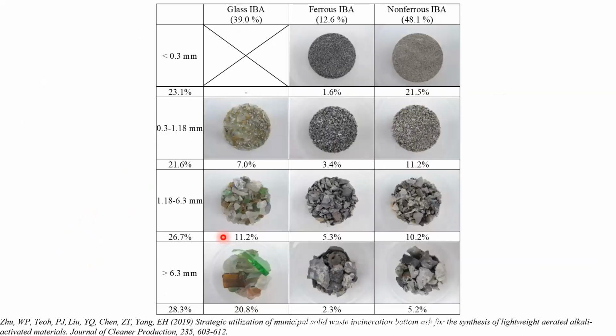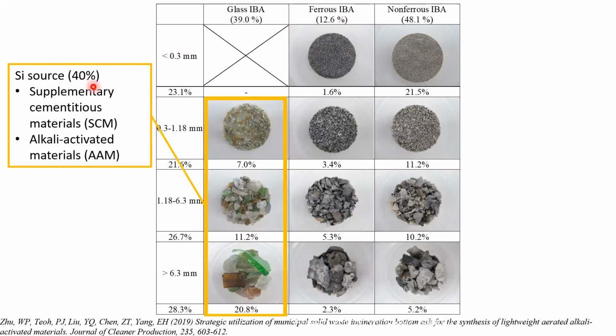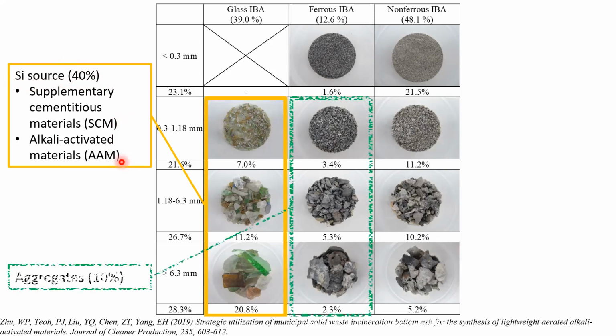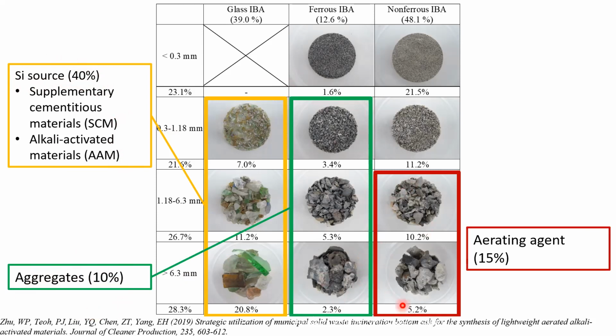With the previous characterization, looking at different size fractions from less than 300 micron all the way to larger than 6.3 millimeter, and different types ranging from glass IBA to ferrous IBA to non-ferrous IBA: the glass portion, about 40%, is very rich in silica, and therefore can potentially be used as a supplementary cementitious material and alkali activated material. As for the ferrous, the larger particles are ideal because of mechanical strength, used as aggregates. For the large non-ferrous particles, because of the high content of metallic aluminum, that could be an ideal candidate for an aerating agent.